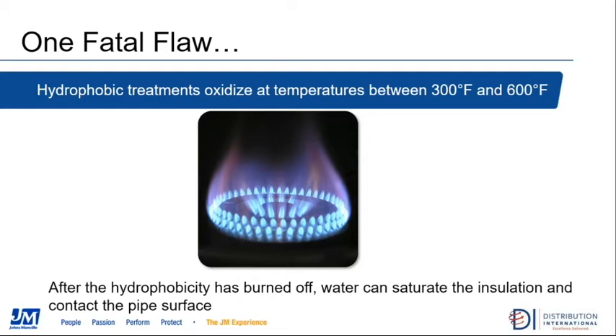So while the inner layer of the insulation will see the process temperature at the pipe or equipment surface, and therefore potentially lose its water repellent properties, the outer thicknesses and the outer surface of the material will likely never see those elevated temperatures and therefore retain some degree of water repellent or hydrophobic properties. However, this can also be a risk in that if water gets into that insulation pipe interface, it will get absorbed into the material that has lost its water repellent property and then get trapped there because the outer portion of the insulation is still hydrophobic and won't allow the water to pass any further.